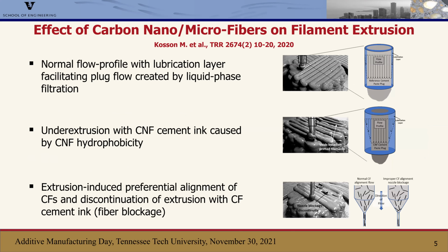So what we found is that when you're printing with what we call a neat paste, which is our paste, which has a cocktail of admixtures in it, but no internal fiber reinforcement, you get this watery surface layer that's caused by the water being driven out into a lubrication layer, as I mentioned, to facilitate that plug flow.